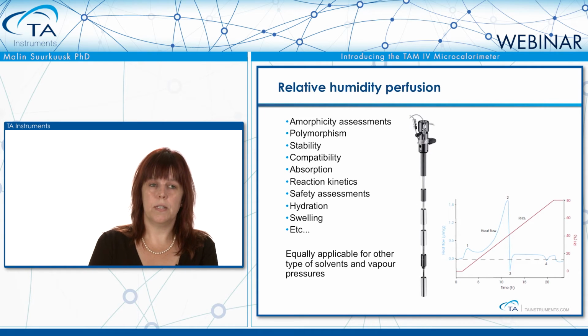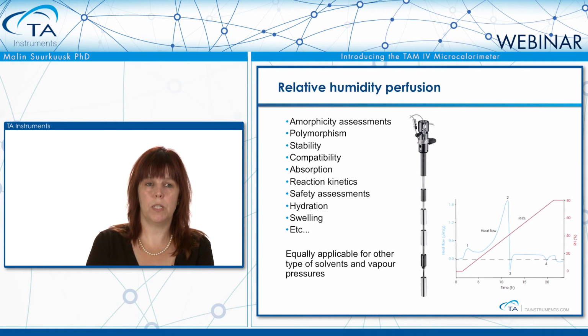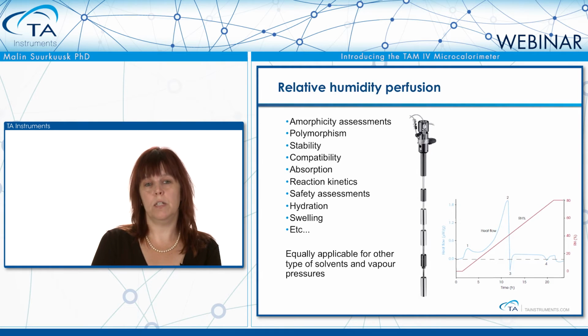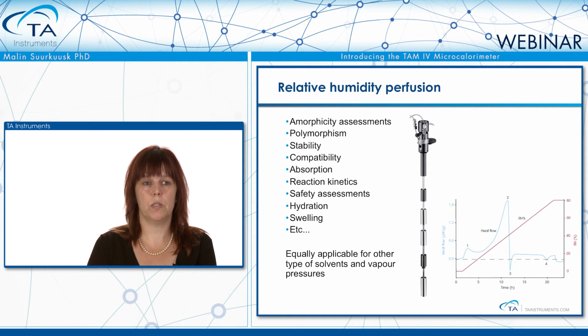At 1, that's where the sample starts to absorb humidity. Once it's absorbed enough humidity, at 2, we have induced a crystallization reaction. We get a peak. Crystalline lactose does not hold water, so the water that was absorbed is now expelled, and that's in 3, where we have an endothermic reaction where water is expelled from the sample. And then increasing the humidity even more, we will have a polymorphic transformation at 4. And we can follow the whole process.